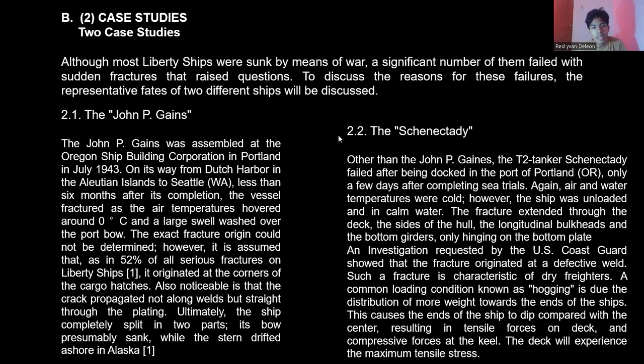Number one is the John P. Gaines. The John P. Gaines was assembled at the Oregon Shipbuilding Corporation in Portland in July 1943. On its way from Dutch Harbor in the Aleutian Islands, less than 6 months after the completion of the vessel, it fractured as the temperature hovered around 0 degrees Celsius. A large swell washed over the port bow. The exact fracture origin could not be determined. However, it is assumed that as with 52% of all serious fractures in Liberty ships.